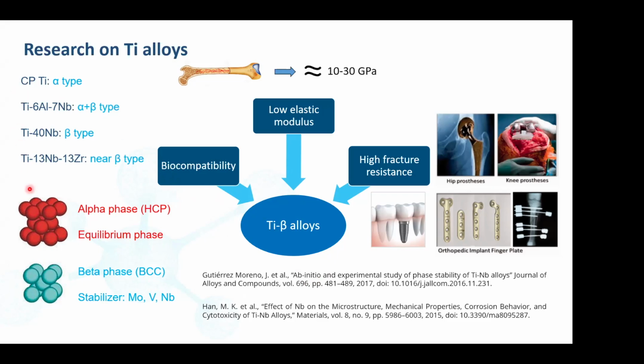So traditionally, the pure titanium will crystallize in the HCP alpha phase, which has some mechanical properties, and especially the elastic modulus of the alpha phase is around 100, 110 gigapascals. And it's usually the microstructure where commercial titanium alloys like CP titanium grade 1, 2, 3, and 4, or for example, titanium 6 aluminum 4 vanadium, which is grade 5, one of the mostly used, or 6 aluminum 7 niobium, which is grade 29, which are an alpha plus beta type.